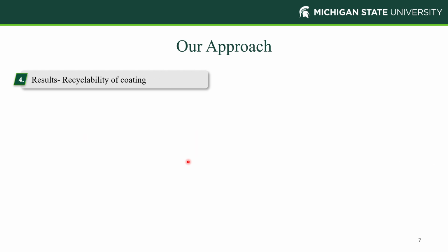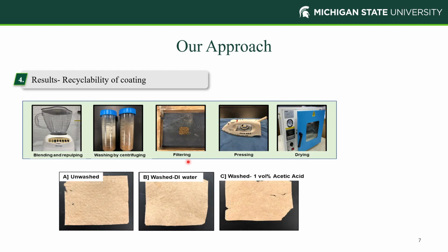Our second part of the research was to validate the pulp recyclability, and in order to validate that, we have a very simple approach that consists of blending and repulping the coated paper, centrifuging and washing it with water and acetic acid in order to dissolve all the coating elements in our paper, followed by filtering of the washable liquids, pressing and then drying, which produces these recycled papers. And we exposed these recycled papers to FTIR analysis to check the presence of coating after washing,